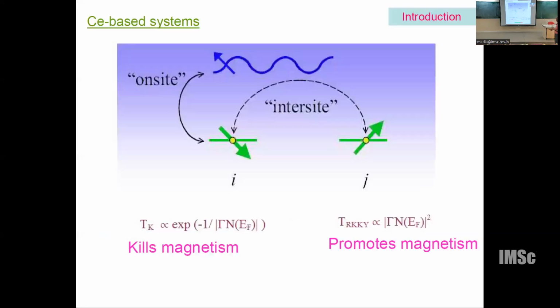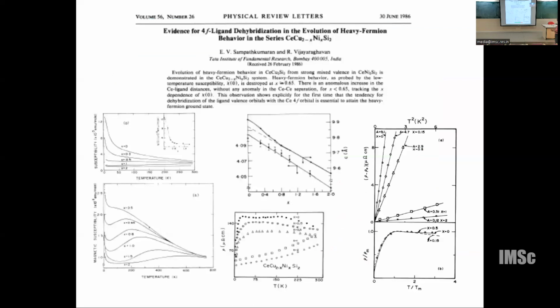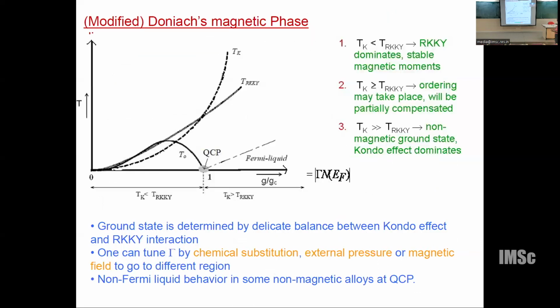Anyway, I don't want to go into details. There are many interesting aspects, and I don't want to go into the detail. The only important thing is that you can modify this. I told you at low temperature you have non-magnetism. You can tune it and make it magnetic. One of the important aspects in the literature is the magnet. At this end, you have magnetism. This is ordering temperature as a function of the coupling strength of the 4f electron with the conduction band.